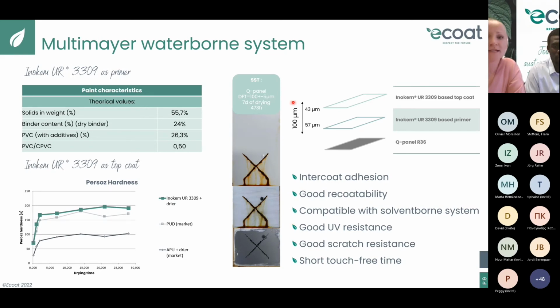top coat. Here in the middle is an example of a double layer. So you have here one layer of primer and one layer of top coat. Both are based on 3309, of course. And you can see here the results at 473 hours. You can see that this kind of system can be a good candidate for the C4 corrosivity category. Finally, you can use Ecoat UR as primer, top coat, DTM, or even base coat.